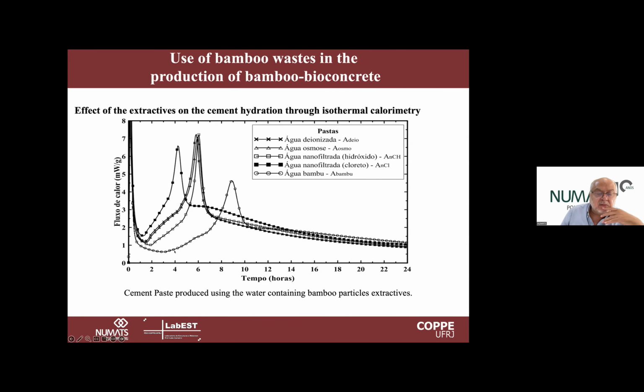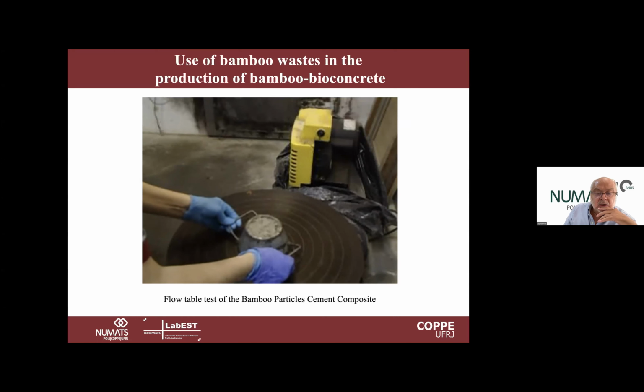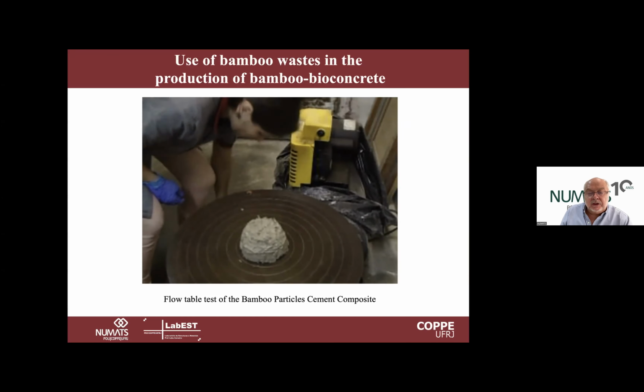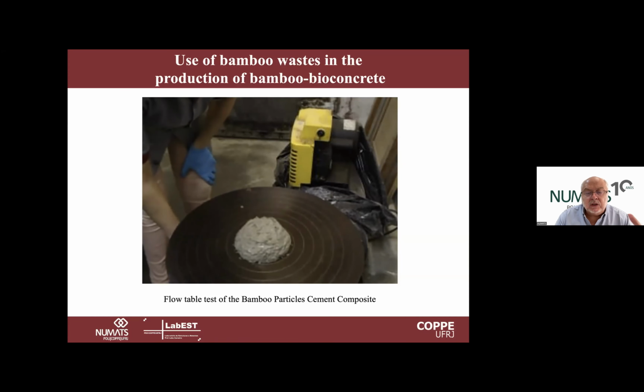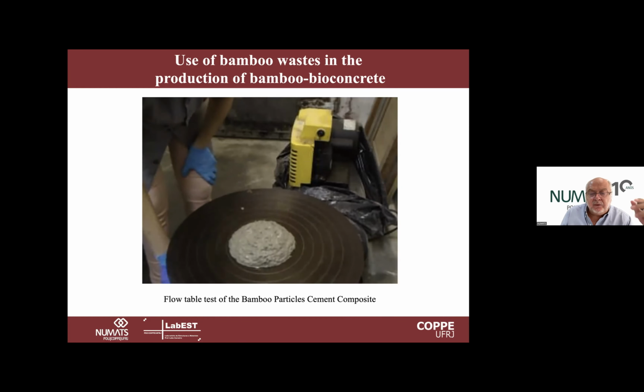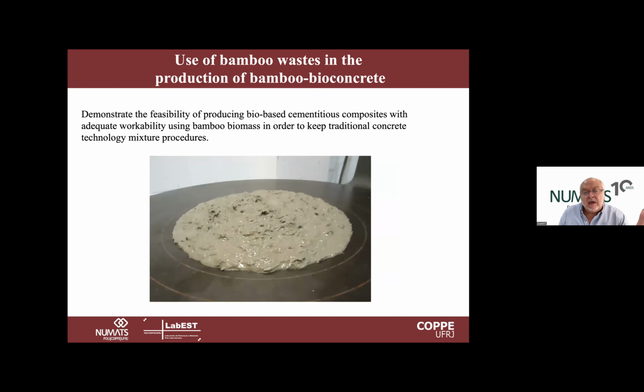We see here that if no treatment is given, the hydration is delayed by 1-2 hours, and also the peak of the heat of hydration is reduced. Then when we use filtered water, doing nanofiltration or reverse osmosis, we can solve this problem, bringing the material to very much the same performance, or even better when we use some accelerators, than the normal cement matrix. You see here the rheology of this material. We can have a material that has good flowability, so it can spread and fill the molds without segregation.